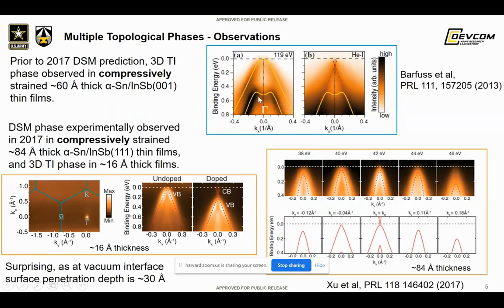You can go from a 3D TI material, and people observe Dirac semi-metal materials as they go to thinner layers. Materials are grown on both CdTe substrates and indium antimonide substrates, but in these slides we're showing only indium antimonide substrates for a reason, because people don't usually use ARPES measurements to observe topological materials when you have CdTe substrates. And because the substrates are not as high quality as indium antimonide, that becomes an experimental problem.